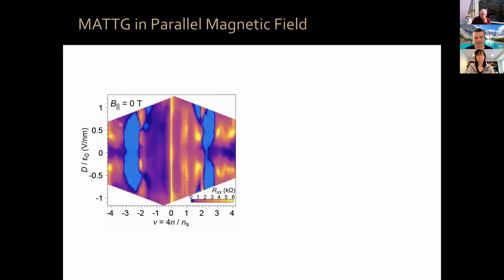Now, let me show you what happens with our system. So we take our sample that we were measuring before in a perpendicular magnetic field, we warm up the system, we rotate it, we put it exactly in plane, okay? We measure again at 0 field, the system looks very, very similar. It has just changed a tiny bit with respect to before. We measure again critical temperature, 2.7 Kelvin at optimal doping and optimal electric field.